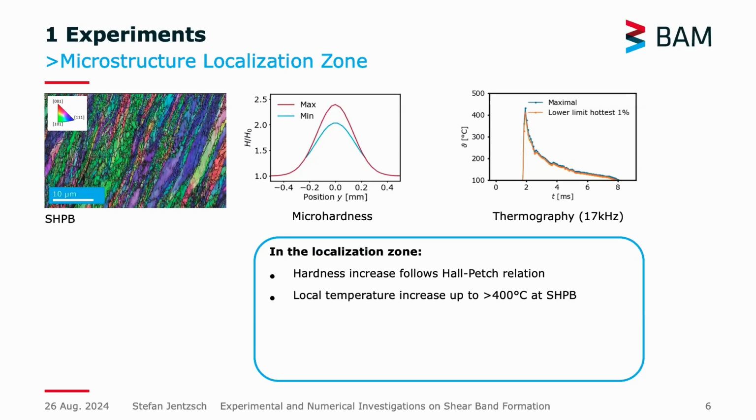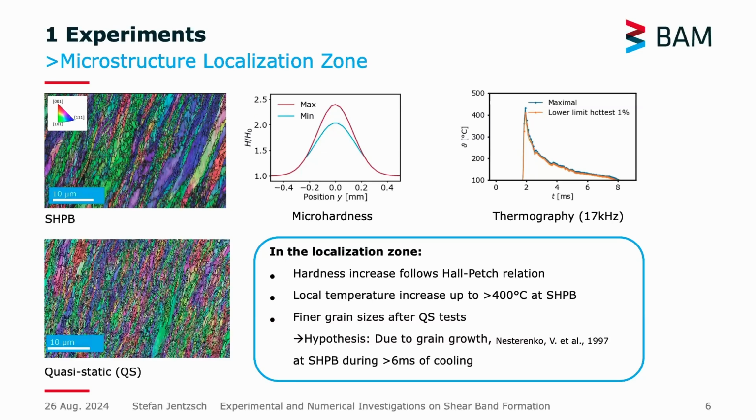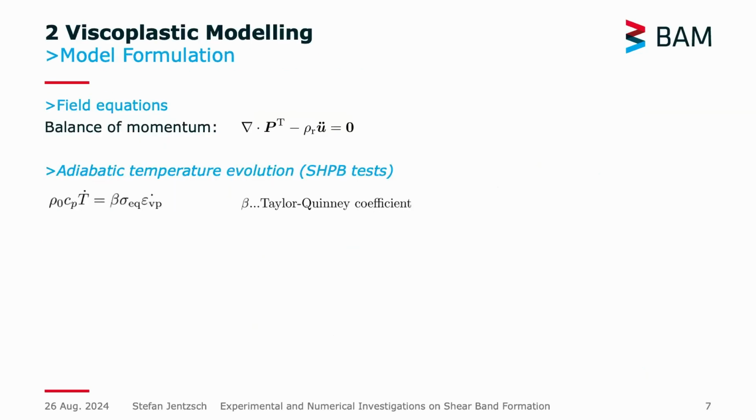Very rapid. Surprisingly, in our experimental findings, for the quasi-static test we got even finer grains. There we hypothesize that it is due to grain growth and further recrystallization stages during the cooling phase. After this experimental introduction, I'm going on with the viscoplastic modeling next.